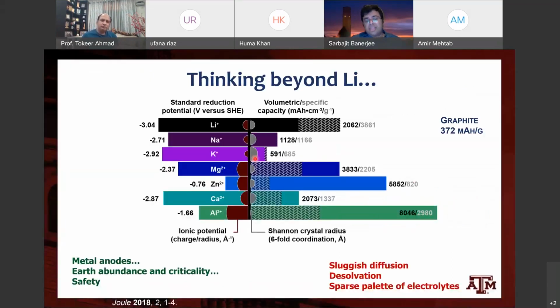So thinking beyond lithium, again, there's a lot of options, and I'm going to discuss all of these in terms of metal anodes. Just to resolve some of the criticality issues with lithium, sodium is somewhat of a drop-in replacement. There's certainly challenges to the chemistry of sodium, and you could move towards using a sodium electrode, which also has challenges, but perhaps those challenges might be less than that of lithium.